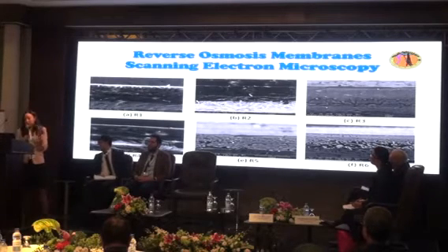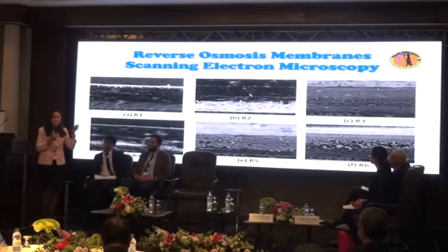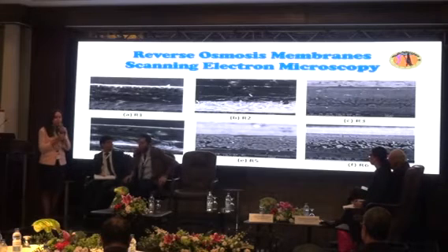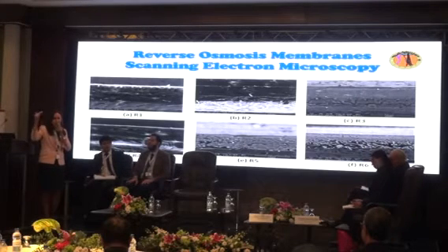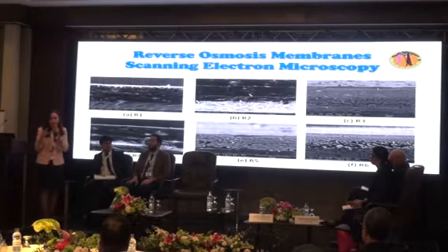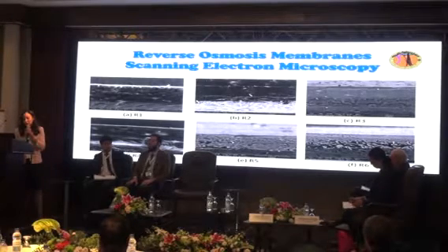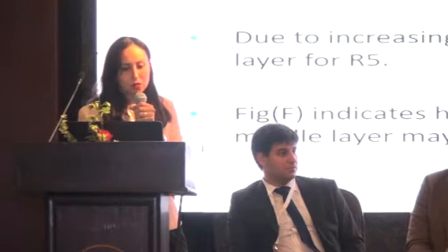But as you see here in membrane number 5, when I increase the percentage of ZnO to 2 weight percent, the polymeric solutions, because they are highly viscous, started to make cracks. So that increased the pore size of our membranes, which is not preferable.